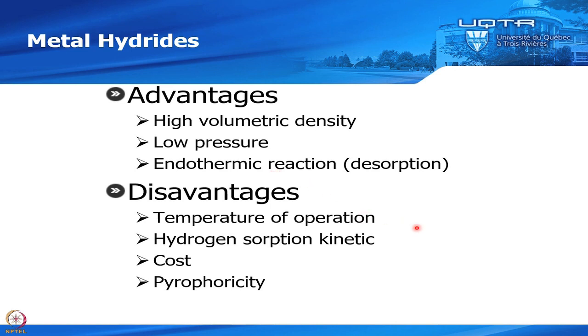The disadvantage is usually you have a high temperature of operation. If you want to have a good capacity, for example, with magnesium hydride, you have to work at high temperature, more than 300 degrees C. Usually the hydrogen sorption kinetics, hydrogenation and dehydrogenation, are relatively slow. The cost, depending on the material, could be expensive. And again, you have to consider not only the cost of the raw material, the cost of the alloy, but also the cost of loading the alloy with hydrogen and putting that in the tank and so on. So the process cost could be quite expensive. So you have to take that into account.